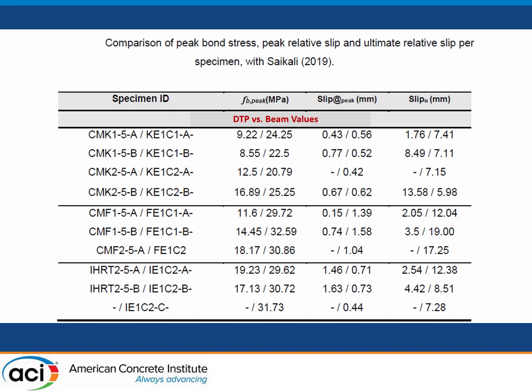So significant attention must be paid to what kinds of specimens we are going to be using and introducing in code practices in order to pre-qualify these materials or the bond for these materials. And the slip at peak is around 0.4 to 0.5 for most of the UHPC materials, lower values for ECC materials, but the slip capacity before pullout is really very large. It's in the order of several millimeters.